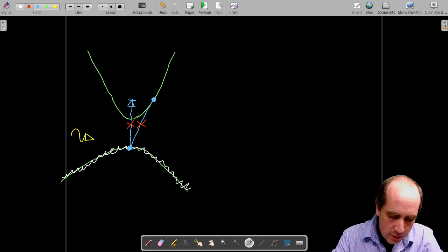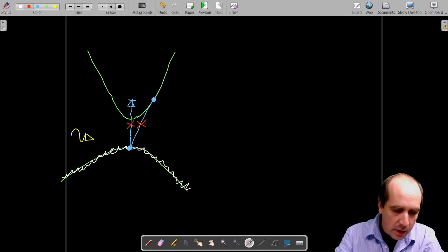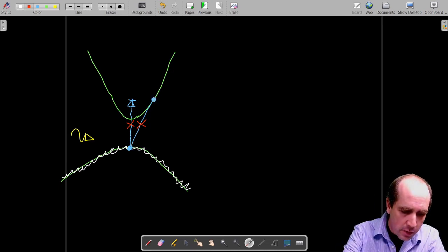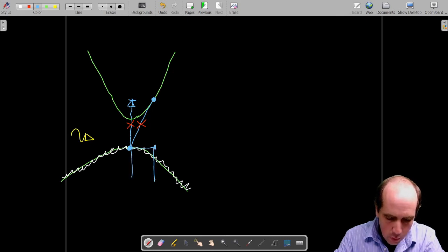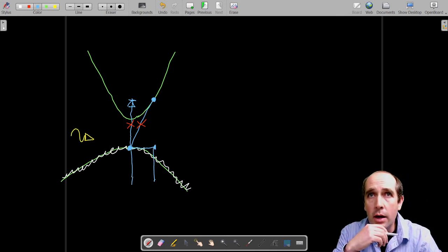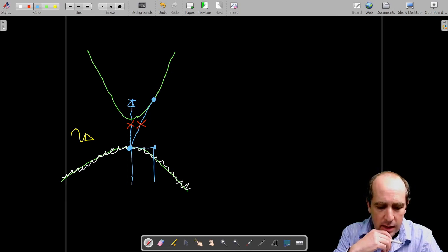And this other transition cannot occur, because if you think in terms of the momentum, the electron will have to change a fair bit. So this electron will have to acquire all this momentum in order to have this transition. And it so happens, as we said in the previous slide, that photons don't carry very much momentum with them. So if there is no conservation of momentum, this transition can actually not happen.